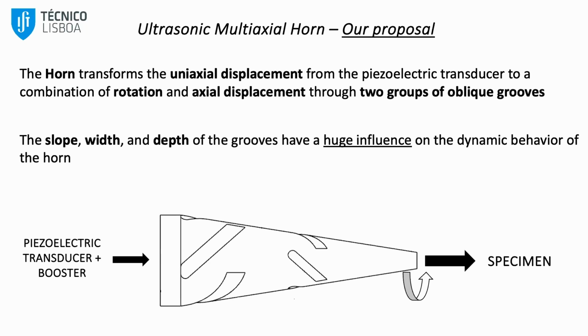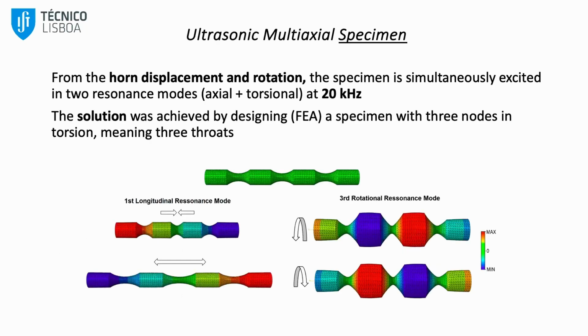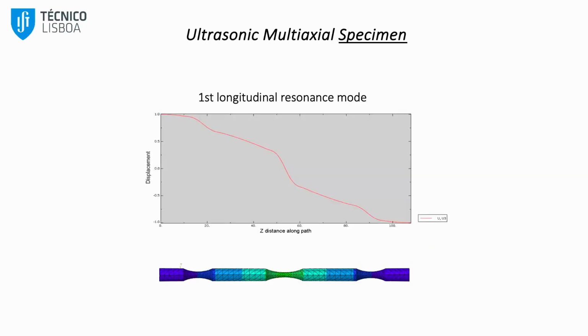So to achieve that, after many attempts, we reached these particular grooves that are very dependent on the slope, the width, and the depth of each groove. So it's two sets of grooves that are going to create these two movements, the rotation and the axial displacement. Okay, so we have performed finite element analysis, and we have finally created and proposed this specimen with 3 throats, as you can see here, and we have tested and simulated them. So here, just for demonstration, can you click on the movie, please?